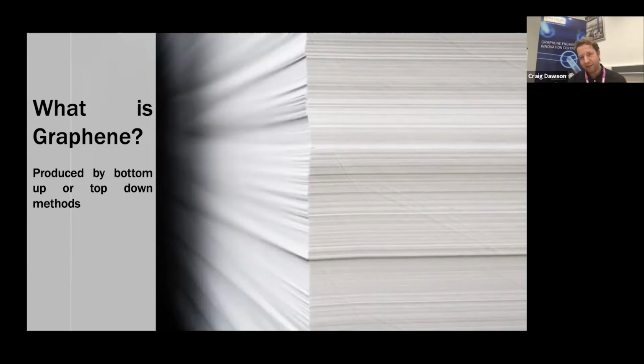Since that time, if we were all here doing the sticky tape, we'd spend a lot of time to produce grams of material, let alone kilos and hundreds of kilos and tons of material required for most applications. So since about 2004, there's been a lot of work in developing processes for producing what we call graphene nanoplatelets, which move away from this ideal monolayer towards a more multi-layer system. They do lose some of those properties as we move towards bulk graphite again. But as long as we're below a certain number of layers, we do retain a lot of those properties, and we can transfer those to the system that they're going into.